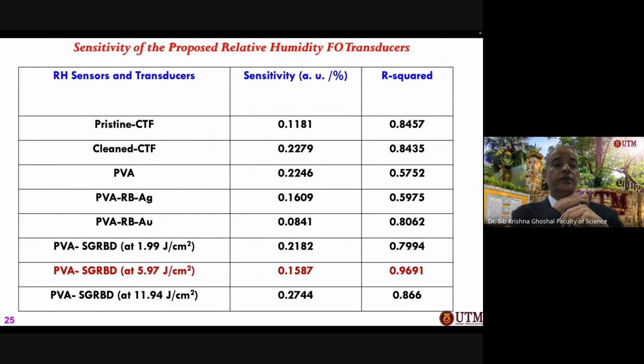So here are the relative humidity sensors and transducers. We have proposed that the PVA coated silver gold rose Bengal dye encapsulated nanoparticles prepared at 5.97 joules per centimeter square fluence have the highest R squared value, which is 0.9691, and a sensitivity of 0.1587, and this is really higher compared to the existing humidity sensors made of traditional materials or some materials made by chemical route. Here, remember, even if we get a little lower sensitivity, we use fewer chemicals, because the pulsed laser ablation technique does not require any extra chemicals or precursors. So in that way, it is very environmentally friendly, and we can get very high quality nanoparticles. That's the purpose of making this kind of sensor.